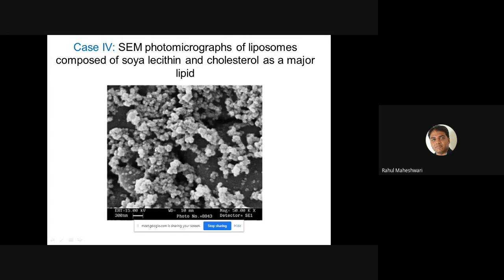As I told you, these liposomes are prepared using the supercritical gas fluid method. So the pressure will be very high in that case. So it is showing the importance of the depressurization stage in the conversion of LUVs to SUVs, meaning large unilamellar vesicles to small unilamellar vesicles. They are not large vesicles, they are small vesicles. So it is recommended that the depressurization to atmospheric pressure occurs at a certain temperature above the lipid phase transition to obtain the highest number of small unilamellar liposomes. Right.